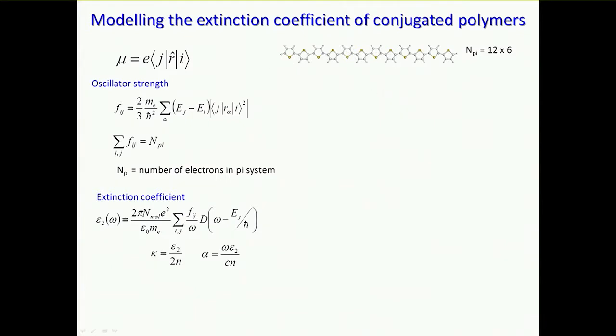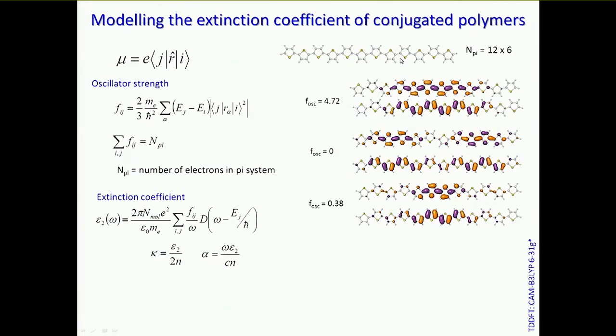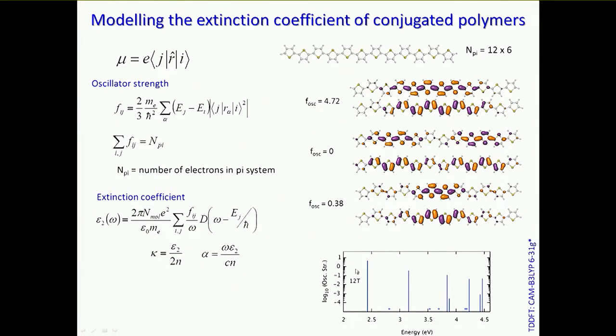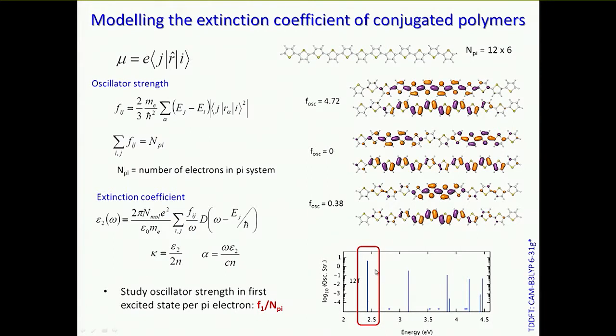So if we take, for example, a dodecamer of thiophene, and we look at the excited states that we get using time-dependent density functional theory, this is the first, second and third excited state as you step up from the bottom. And you can see the first excited state has quite a high oscillator strength. The second one is completely dark because it's symmetry forbidden. And the next one is symmetry allowed, but it's not so strong. And we can go on and build up a spectrum. And this is on a log scale. And we see this is the visible region here. So as far as solar cells are concerned, it's clearly the first transition that matters.